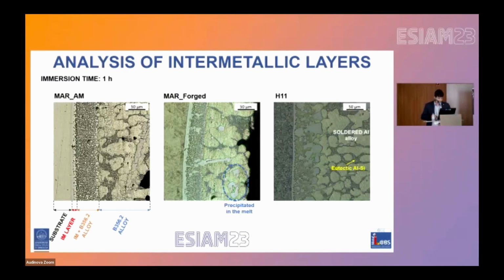However, the thickness of the intermetallic layer, together with the shape and size of the intermetallic particles, differs between the considered samples. In this case, the thickness of the layer on the maraging forged sample was thicker, while the less thick layer is that of the H11 sample.